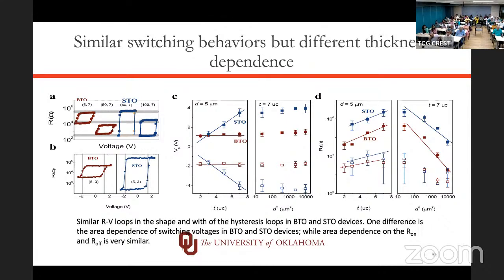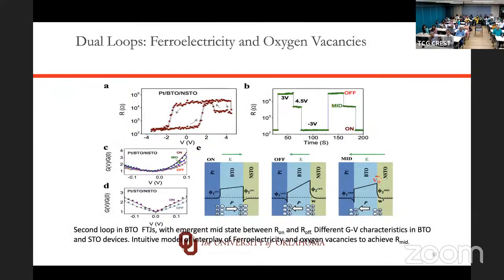You can also have both phenomena exist in the single device. So here, for example, is barium titanate, where with the increase of voltage, this is essentially tunneling-induced behavior. But here, oxygen vacancy can also start diffusing in barium titanate. So you get now another very interesting memory characteristic from oxygen vacancy diffusion.